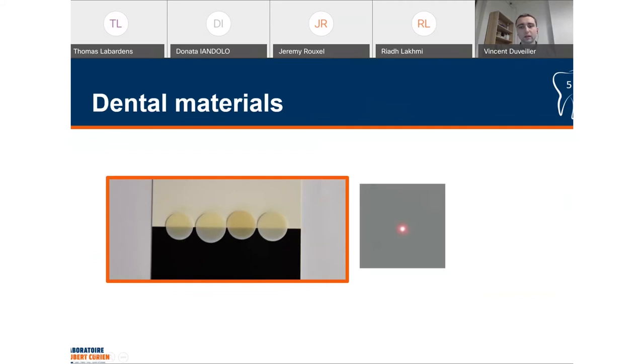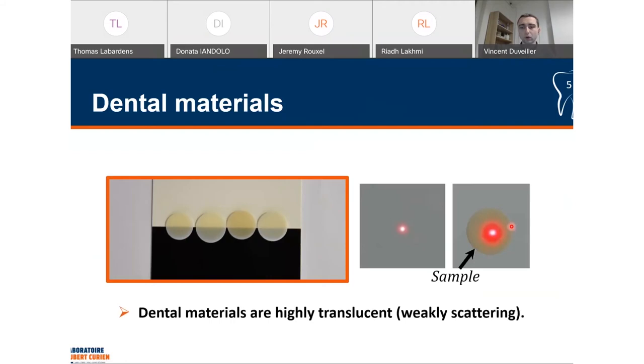Translucency can be assessed using a laser beam. Here you can see the impact of a laser on a white paper, and here the impact of a laser on a sample of dental material positioned over white paper. You can see the large halo here, which is characteristic of a highly translucent material. Translucency makes it difficult to predict the material's appearance because it's not something that is taken into account by the most simple optical models, like the Kubelka-Munk model that I will tell you about. Instead, these models assume the material to be highly scattering, but it's not the case here.